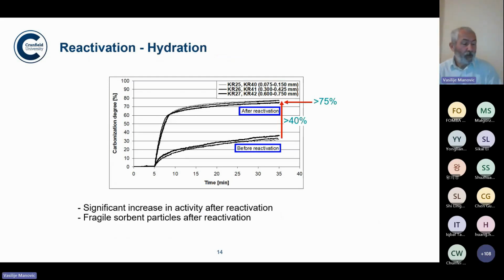Another possibility to recover material, to increase activity after it's spent, is hydration. Just to give you some idea of what we have been doing, how we were trying to improve material performance in the calcium looping system. I think that material was after maybe 30 cycles, and the conversion, as you see, even after half an hour, was only 30%. In the first cycle, when you start using the material, it's usually at least around, say, 60-70%. So this material is not contributing much to CO2 capture. So one of the best techniques to reactivate that material was to expose it to steam.